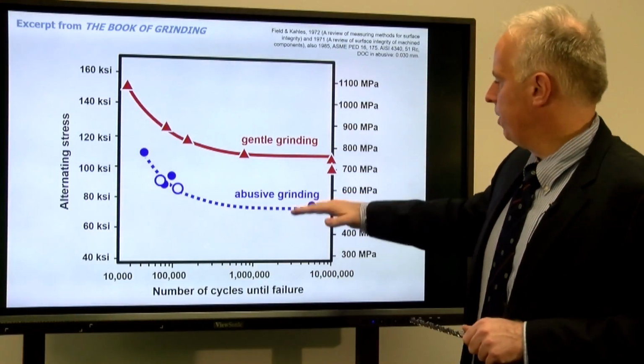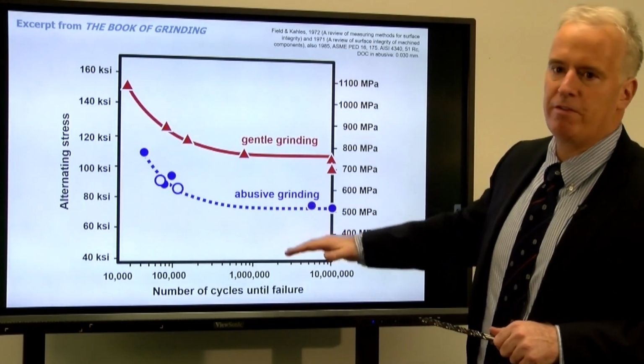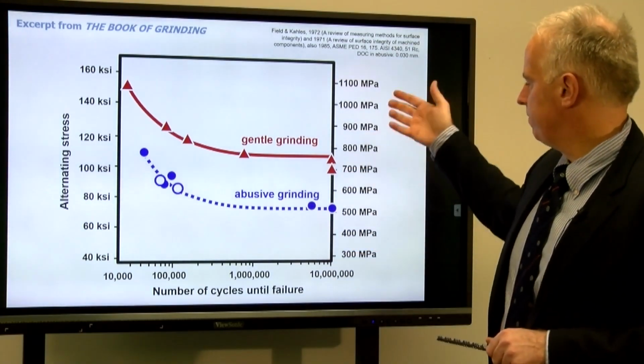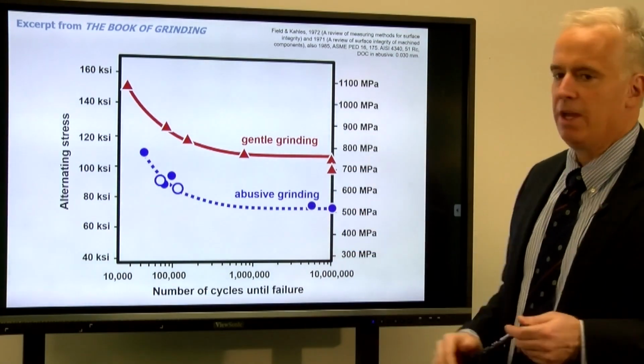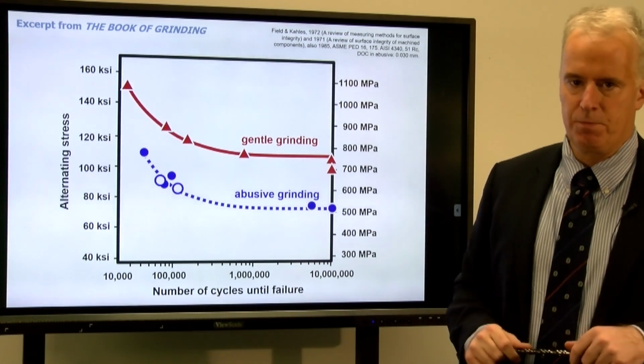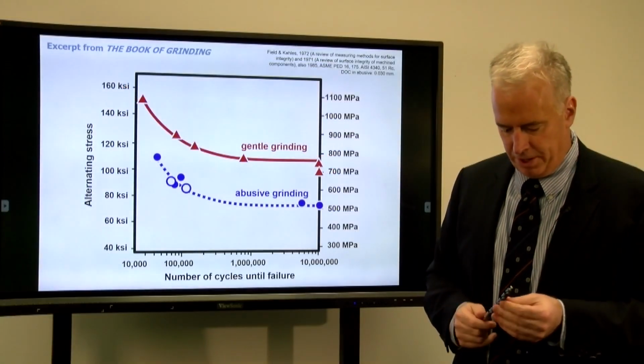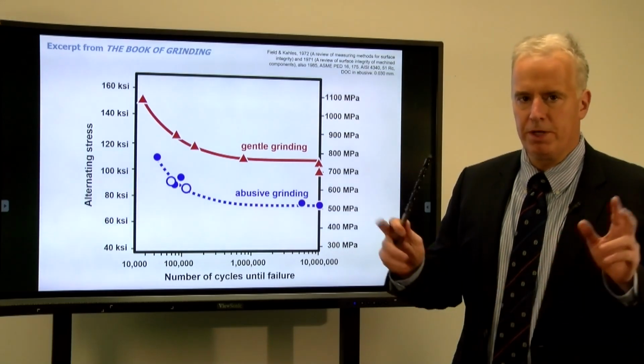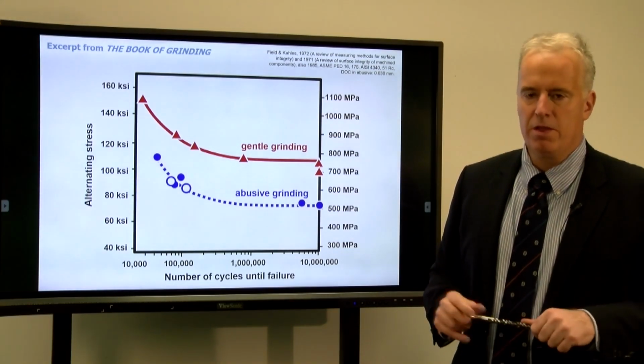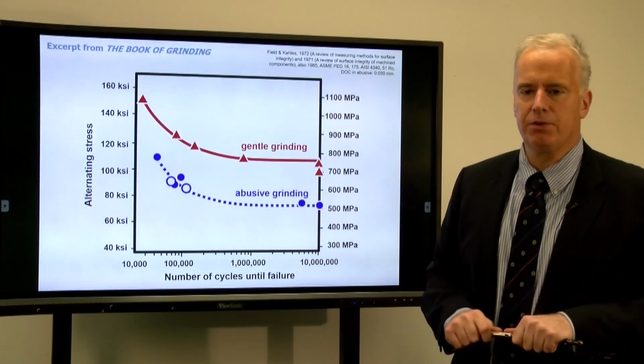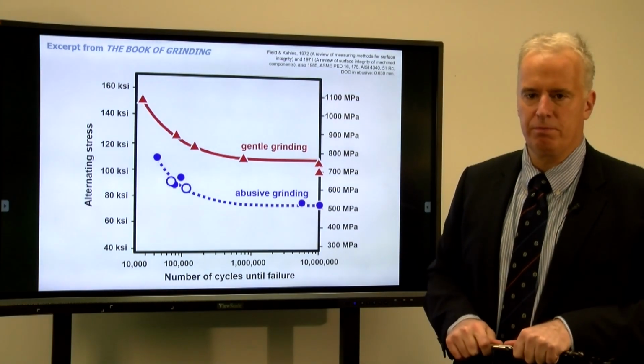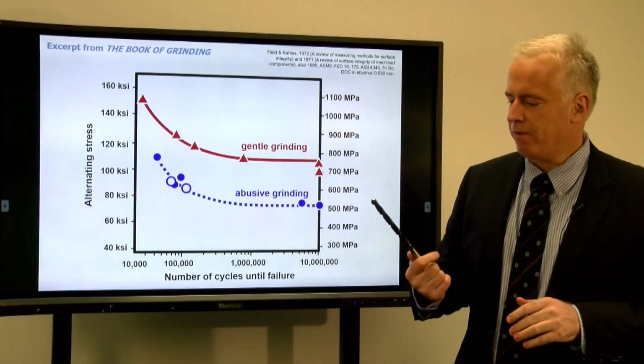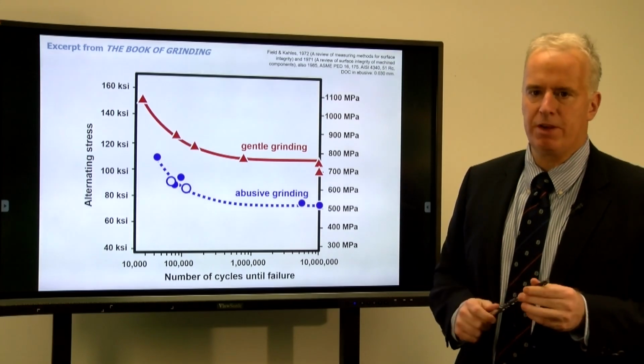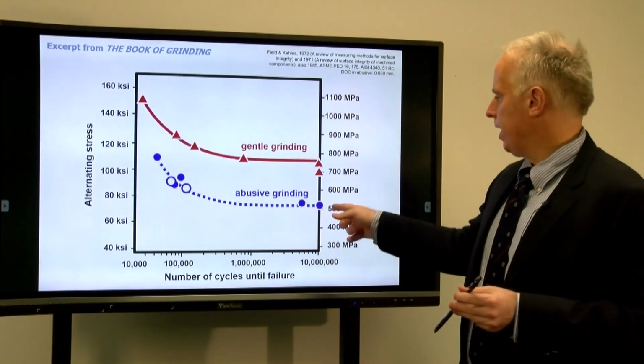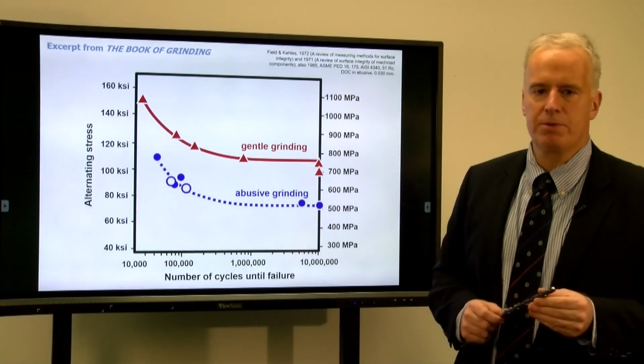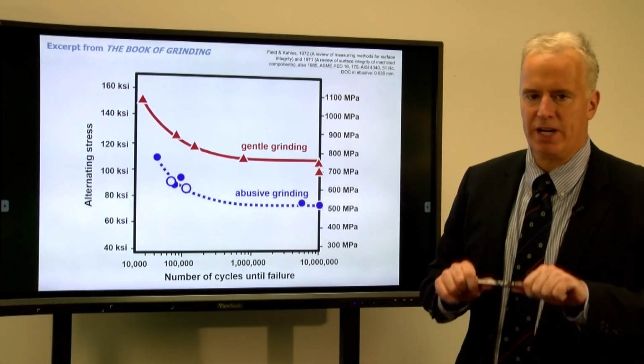And then that cutoff point where we can cycle it forever before he breaks is now not 750 megapascals, it's only 500. Okay, so the moral of the story so far is if you burn the workpiece, depending on how you define burn, this guy is not going to have as many cycles before he eventually breaks. Or if we want to guarantee the thing will never break due to fatigue, we're going to have to apply a much lower cyclical stress before the guy eventually cracks up.